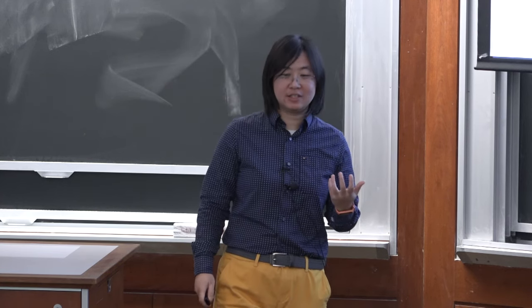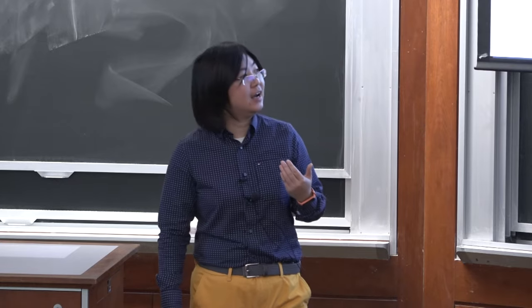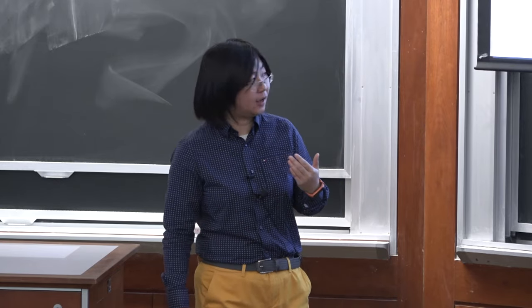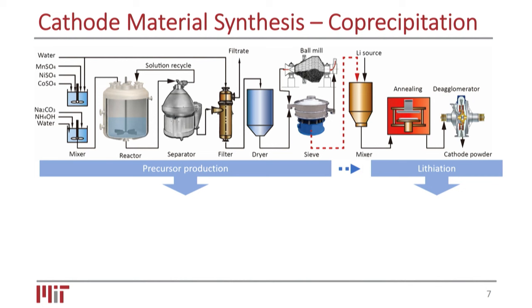So before I dive into the technology that our group is particularly invested in, I want to show you the current state-of-the-art manufacturing method for lithium battery cathode materials. And that is called the co-precipitation method. And based on its name, you could see there is a co-precipitation process and another process called lithiation. So in short, for the multi-component metal oxide, except lithium, all the precursors would come into play in solutions. And in this process, by adjusting the pH, we can get the co-precipitation of the precursors. And that's called the precursor production.